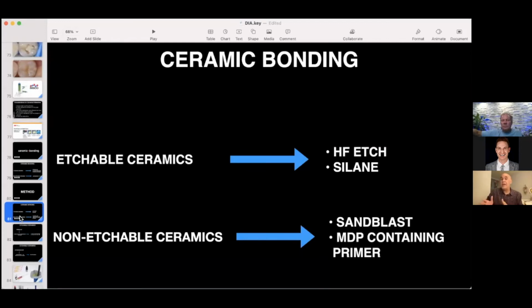Now, on non-etchable ceramics, which is basically zirconia, you're going to have to sandblast, and you're going to have to use an MDP-containing primer. Why MDP? Because MDP has a chemical affinity to zirconia. No other organophosphate or adhesion promoting monomer has that affinity. You're going to achieve bond by using MDP, not by using something else. Once you sandblast it, you have achieved mechanical retention. Whatever you put on top of that is going to bond, sure, but it's mechanical, not chemical. MDP will bond to zirconia, 100%. It has been proven. It has been published.